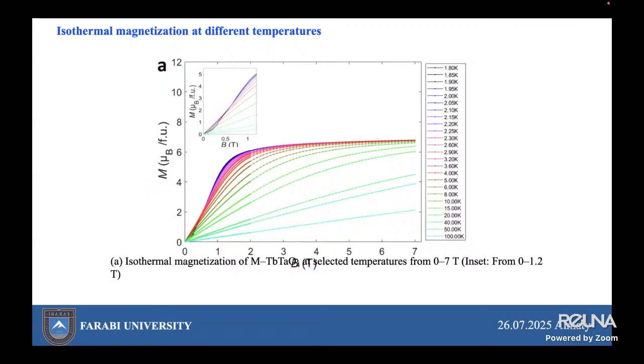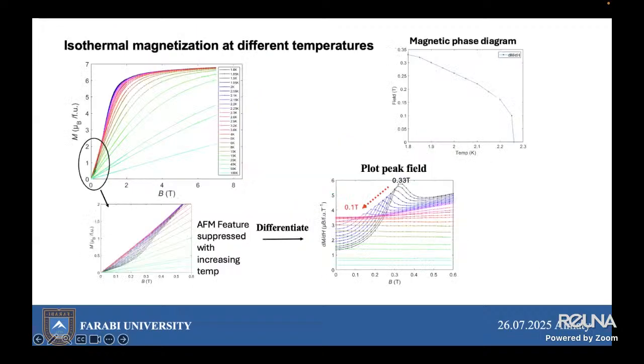And the differential magnetization as a function of applied magnetic field, isothermal magnetization at different temperatures, and magnetic phase analysis. This composite figure illustrates isothermal magnetization behavior of the material at various temperatures. You see that from 1.8 Kelvin until 100 Kelvin, and how it evolves into the magnetic phase diagram via differentiation and peak analysis.